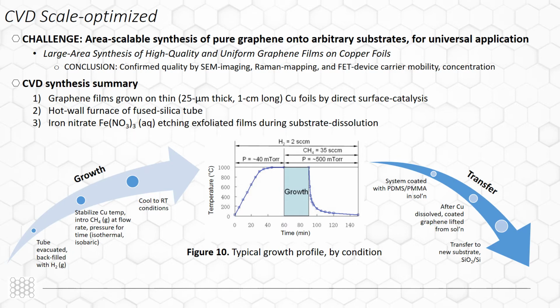This growth process principally occurred over a 30-minute interval under isothermal and isobaric conditions and followed by furnace cooling to room temperature at about 60 minutes. This cooling rate was also considered from 40 to greater than 300 degrees Celsius per minute.